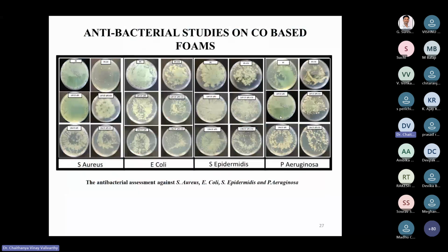So these are the results for antibacterial studies on CO based foams. When CO is added, there is antibacterial activity, but it is very low. But with silver nanoparticles, we got very good behavior because silver nanoparticles have highly antibacterial properties. We can look into other nanoparticles also, which are very low cost, because silver nanoparticles are a little bit expensive compared to other nanoparticles, and which possess an antibacterial property.